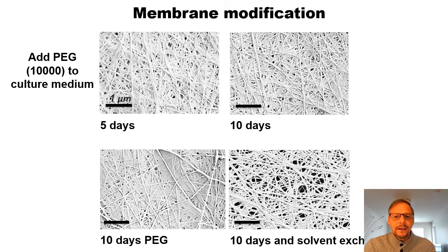So here we have the case of incubation for 5 days and for 10 days, and in the top row you can see how the pellicle, or the biofilm, or the membrane becomes more dense just by letting the bacterial cellulose produce more and more cellulose ribbons. In the bottom, you see exactly the same, but in the presence of PEG, after 5 days and after 10 days.